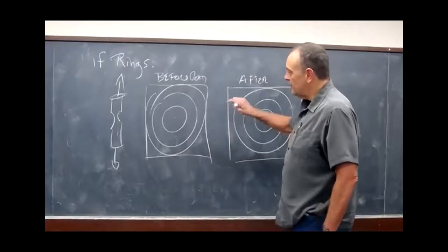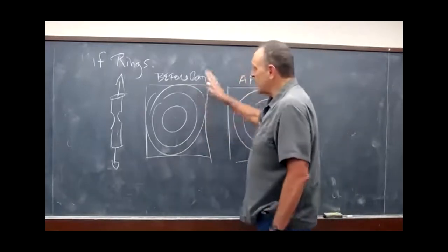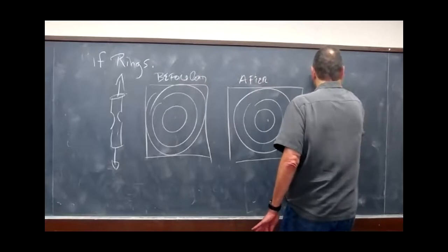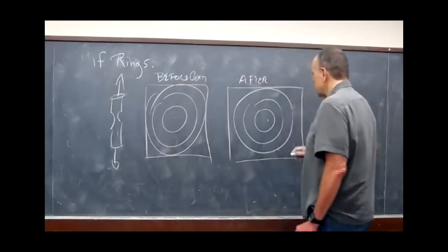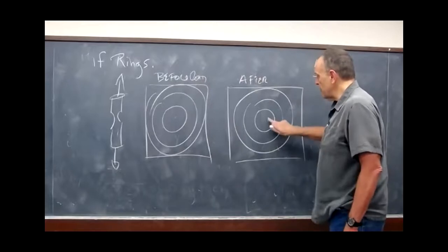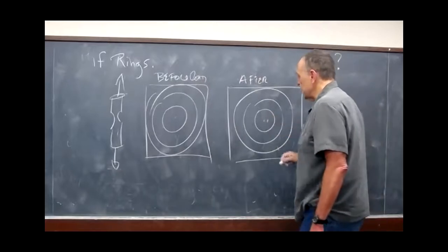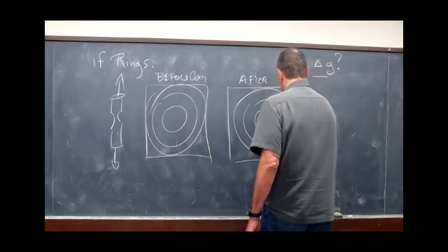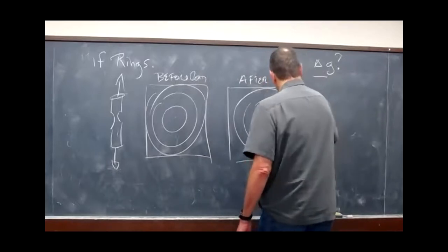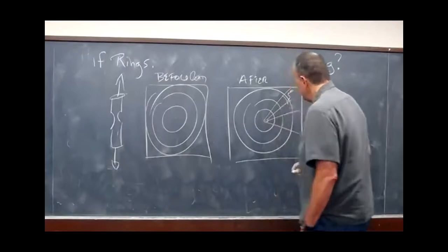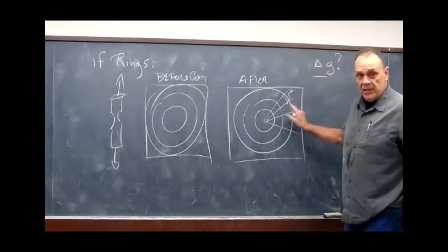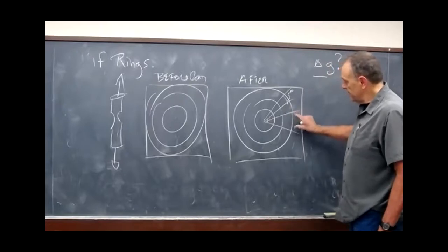Well, anyhow. But how do I get to, let's have a question. So how do I get to my delta G? How are you going to do that? And Darren will probably talk about this at some point. So what you do is you break this thing up. You divide this up into sectors, and maybe you do 5-degree sectors, and then you integrate these sectors in omega and take an average.